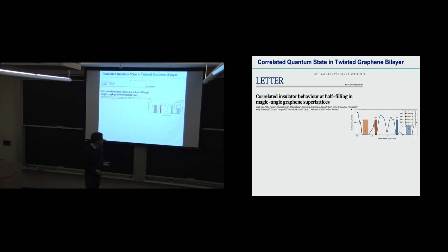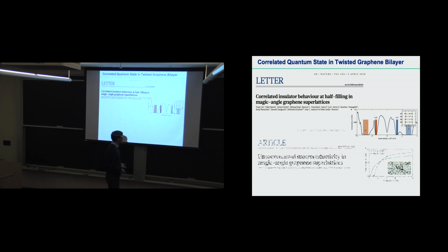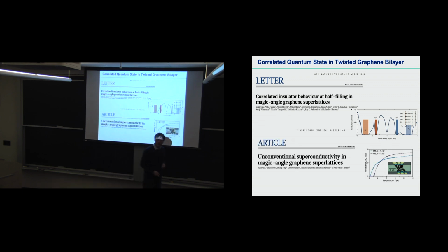And what surprise comes afterward is that if you dope this correlated insulator, like in analogy with the cuprates, it becomes a superconductor. Well, the superconducting transition temperature is reasonable, say about a Kelvin or so - not too high, but nevertheless the surprising and exciting part is that there might be some interesting connections one can make with another important problem, such as the cuprates, just by looking at this correlated insulator, doping it, and creating a superconductor. There's kind of some exciting connections one can make.